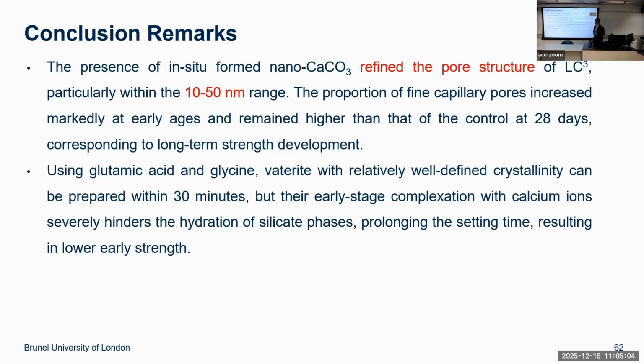We also use amino acids. We have looked at two amino acids, glutamic and glycine, and their effect on the different phases of calcium carbonate. We found that vaterite with relatively well-defined crystallinity can be prepared within 30 minutes. But the early age complexation with the calcium ions seriously hinders hydration of the silicate phase. So this prolongs the setting time and reduces the early strength. So this is the trade-off.